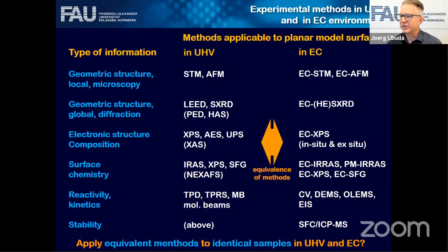If you do not control the potential and bring the sample into an electrolyte, you immediately have electrochemistry going on, and you also have a backside of the sample and sides of the sample, and you cannot control what is going on there. To our experience, the best method, if you want to keep the sample mostly in the state that you have prepared it, is to do the transfer into ultra pure water to protect the surface, and then transfer, for instance, into some electrochemical experiment. And once you make the contact there, you immediately have the potential control. So if you transfer, for instance, into a cell where you do infrared spectroscopy, as soon as you contact the electrolyte, you want to have the potential control. So that's what we mostly do.